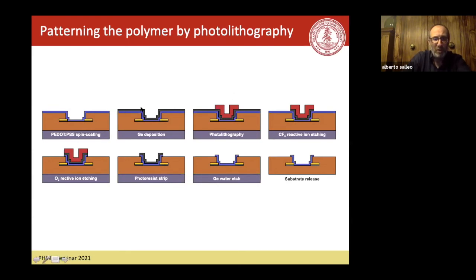So we deposit a layer of germanium everywhere. And then we do our photolithography. So here's a photoresist. It gets patterned to reveal essentially the channel. Then you etch the germanium. This is a dry etch of the germanium. So you go down to the sensing polymer, but now you want to remove this part because you only want to sense here in the channel. So you etch with oxygen.